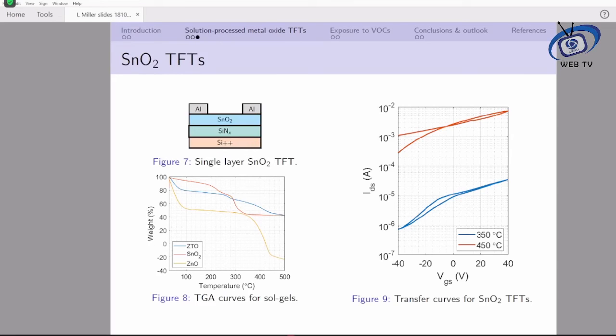The thin film transistor annealed at 450 degrees Celsius had increased mobility, which is consistent with the results presented previously. The thin film transistor annealed at 350 degrees Celsius could have contained a greater proportion of metal hydroxide bonds due to the incomplete dehydroxylation and condensation processes, which then acted as traps and hence hindered electron transport.